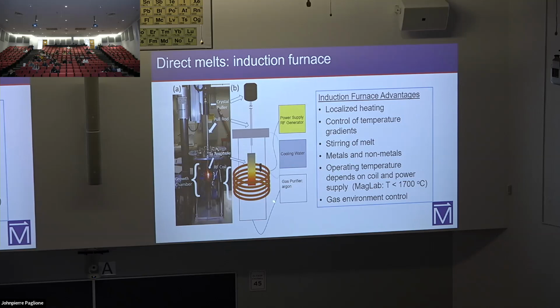Operating temperatures are variable depending on the strength of your power supply. Ours is a 6 kilowatt, but there's much more powerful systems out there, and it depends on how many turns you make and the diameter of the coil and so on. But it's pretty straightforward to get to temperatures as high as 1700 degrees C. And that's significant because the resistive furnace that you're going to buy from MTI is probably going to get you to 1100 or 1200. You can spend more money and buy a nicer furnace and get to 1500.